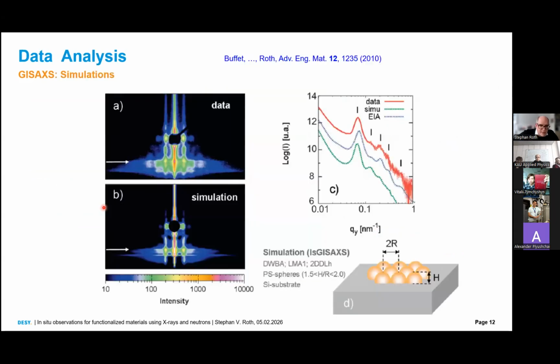To analyze the GISAXS, to show you directly here, we are able to simulate the scattering pattern. This is again a 100 nanometer polystyrene colloid sprayed on a surface with slightly different parameters than shown beforehand. And if we look into this cut again, this is the red line, we see again the maxima and minima. We can make what is called an effective interface approximation, where we assume a certain structure and size and just calculate via particle form factor and structure factor the scattering pattern. Or we make a full two-dimensional simulation, and this is the green line. They are just shifted for clarity. You see that we can quite well reproduce all the features of the experimental data, and in this specific case, we could even tell how many layers of colloids are on top of each other.